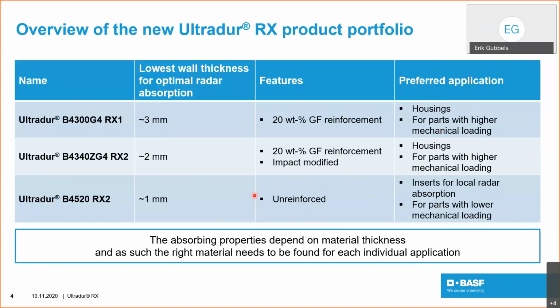This final material, as you can see, is unreinforced. It has been designed specifically for very high electromagnetic wave absorption, especially at low thicknesses, as you can see from the 1 millimeter. However, this changes the mechanical properties because it's not reinforced. Therefore, we feel this material is more suited for inserts for local radar absorption inside a radar sensor, for example, or for parts where lower mechanical loading can be expected. Nevertheless, the absorption depends on the material thickness, which we'll come back to in a few seconds. As such, the right material needs to be found for each individual application one could consider.